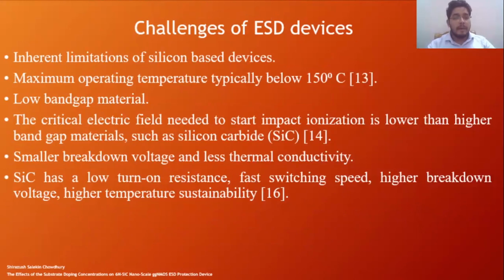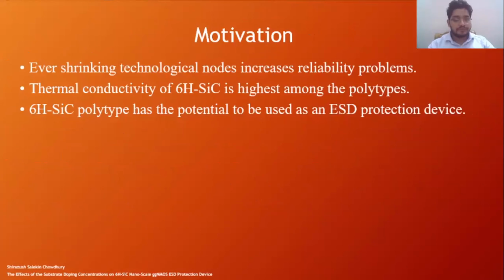Silicon-based devices have a maximum operating temperature typically below 150 degrees Celsius. As silicon is a low bandgap material, the critical electric field needed to start impact ionization is lower than in higher bandgap materials, such as silicon carbide. Silicon carbide is a wide bandgap material that can function at extremely high temperatures, up to 600 degrees Celsius. Being a wide bandgap material, silicon carbide has a low turn-on resistance and fast pulse switching speed.